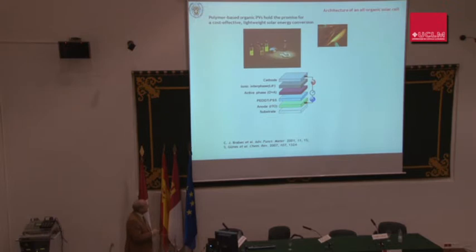So, here is a basic scheme. It has already been shown in previous lectures, but what I would like to show you is how simple it is to prepare these cells. You need a substrate, which is typically glass or plastic, and you need the anode, which is transparent, as was already mentioned before. This is indium-doped tin oxide, ITO, a transparent electrode. The cathode is typically a metal such as aluminum, calcium or magnesium, and then you have the active phase, which is the mixture of donor and acceptor. Different evolutions have been used, as I will mention later. What you have in between the electrodes and the active phase is just a polymer or an ionic interface, typically lithium fluoride, which in general allows better contact and better transport of charges to the electrodes.